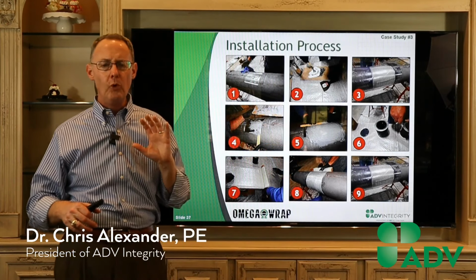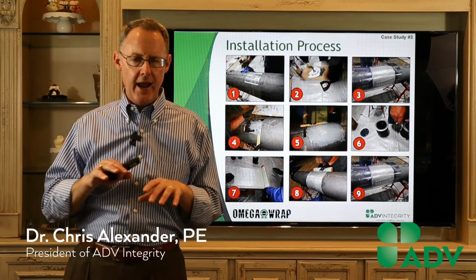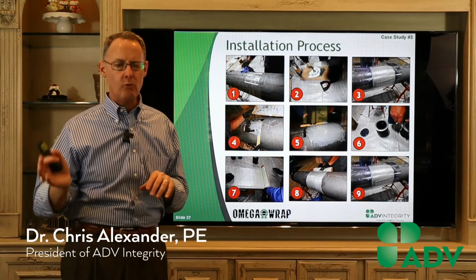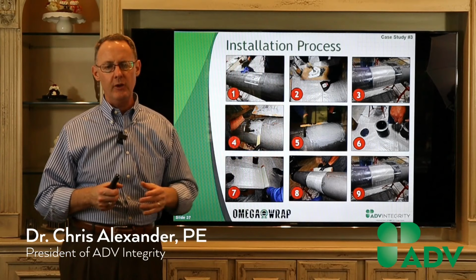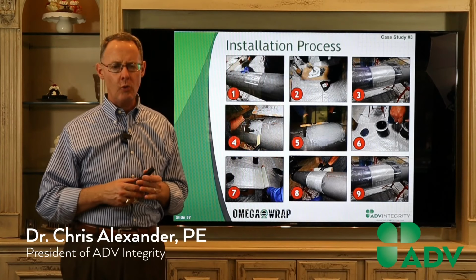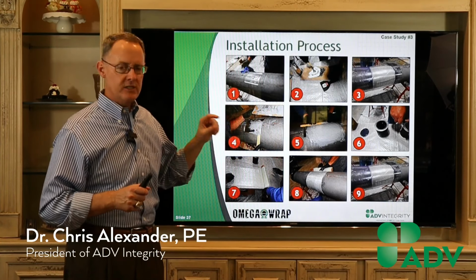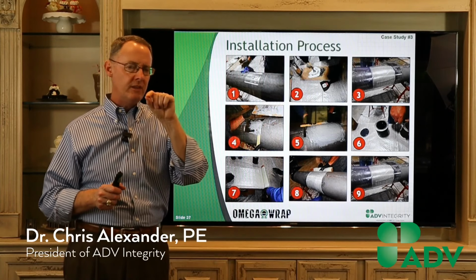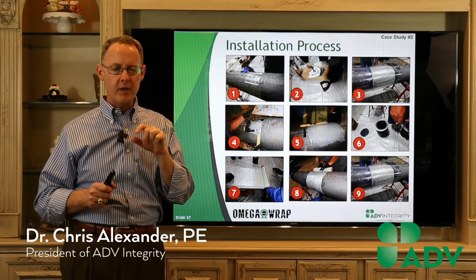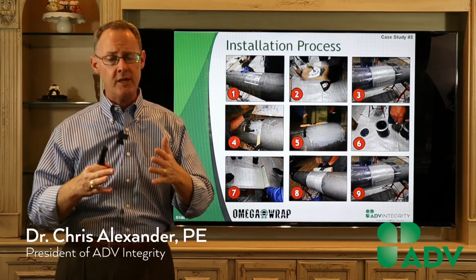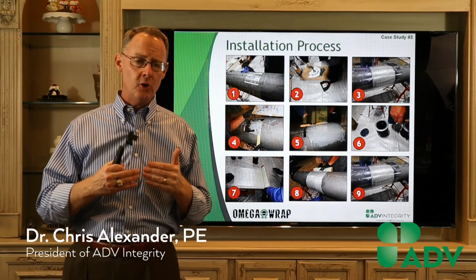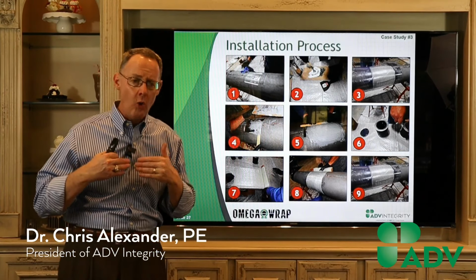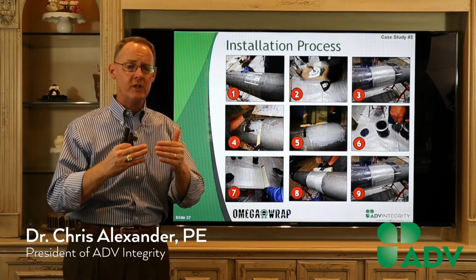This is called the spool survival test, and it has a relatively thin wrap. If we were doing this out in the field, we would probably have something closer to 3/4 of an inch. But these repairs are relatively thin, typically less than 1/4 of an inch, because what we're going to do is pressurize, and we want to make sure that material and the filler material all work together and get us to a minimum pressure. So that's what happens. We let it cure for a day or so, and then we basically do a pressure test.